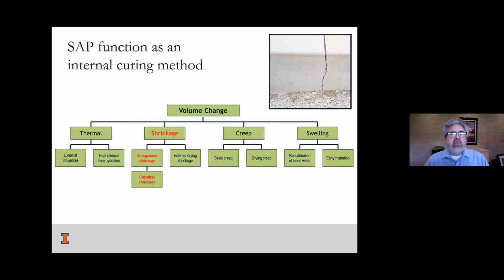Okay, the idea here with SAP is that we're going to add this material as a powder into the concrete truck and use its ability to hold on to water and then release it later on. There's sort of a competition for water, and the SAP particles will win that competition when there's an abundance of free water. And so they'll swell up in those first minutes of contact with our concrete.